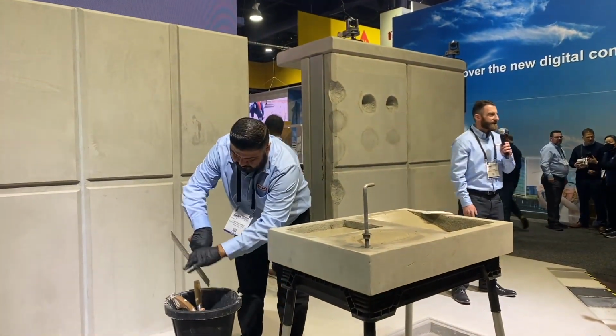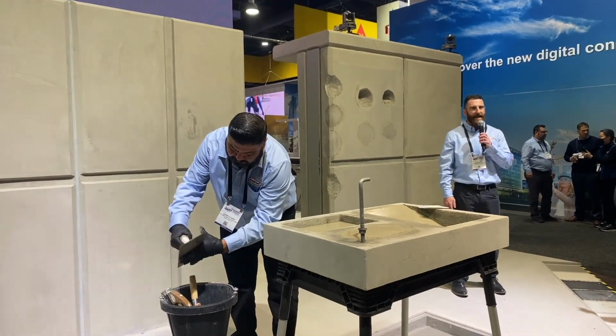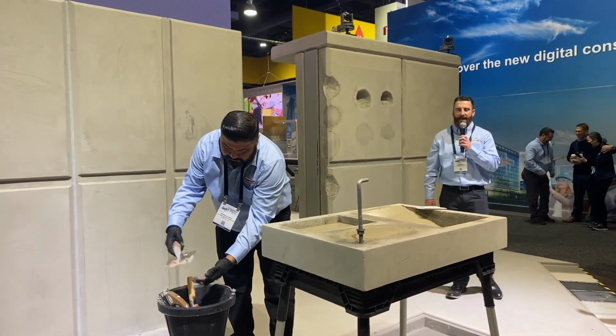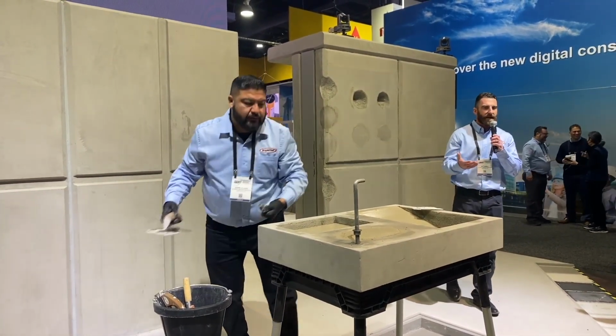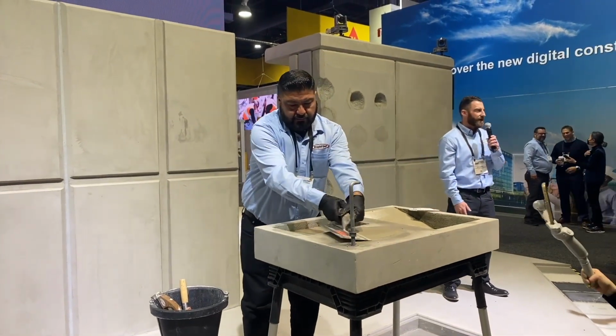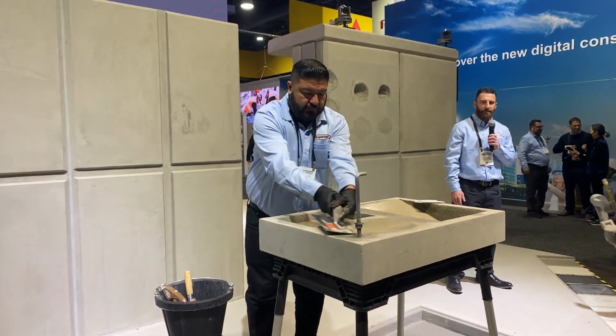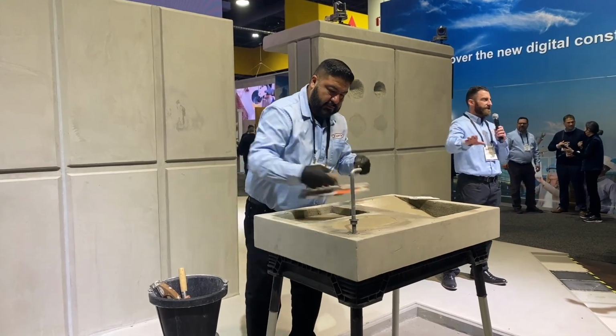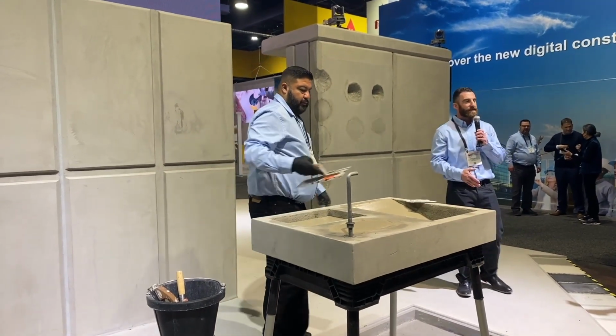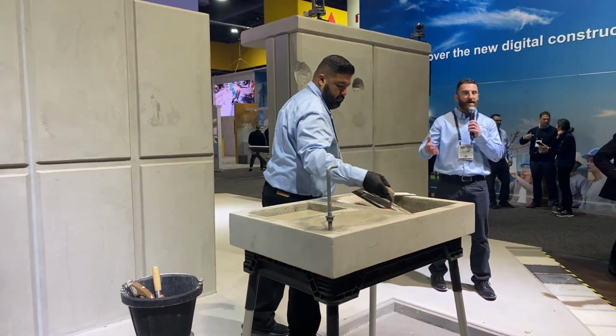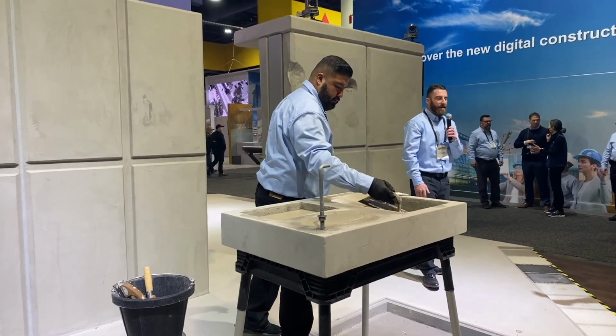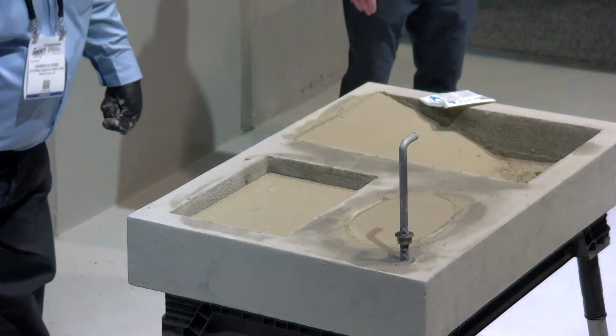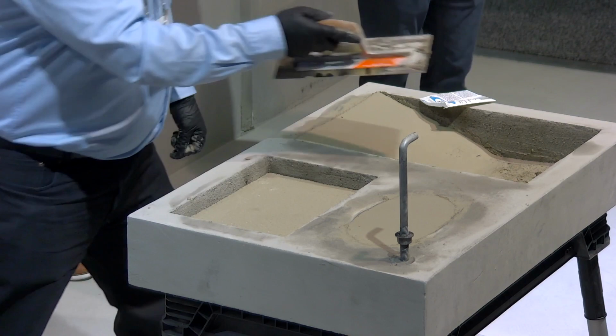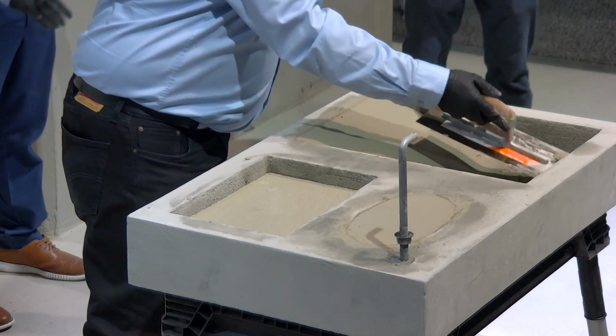Now, the ultra-fast anchoring adhesive has undergone rigorous testing to get ICC and NSF certified. The NSF means that it can be used with or adjacent to potable drinking water. It's great in a wide range of temperatures, can go all the way down to 14 degrees Fahrenheit or up to 104 degrees Fahrenheit. And it also has a very high heat deflection temperature, so that means in very hot temperatures, it won't soften.